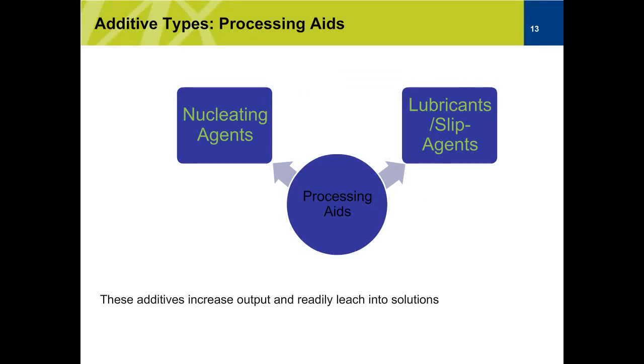The second type of additives that we see a lot in leaching from labware is processing aids, and basically they are divided into nucleating agents, lubricants, and slip agents. So nucleating or clarifying agents, their function is really to increase the overall crystallization rate of the polymers. High crystallization speed means that you will solidify the polymer at a faster rate when it's cooling, which means that you have a reduced cycle time, which means you're going to increase production, which means you're going to decrease cost.